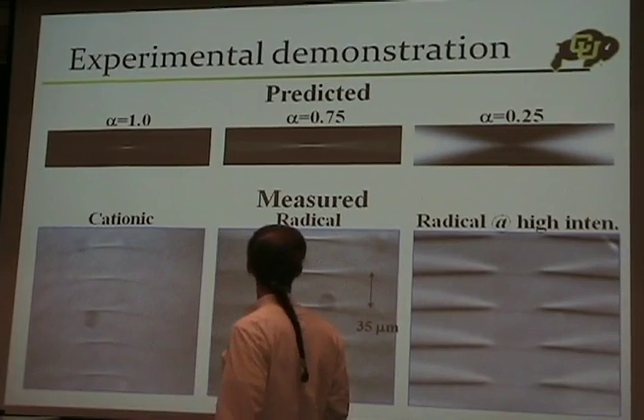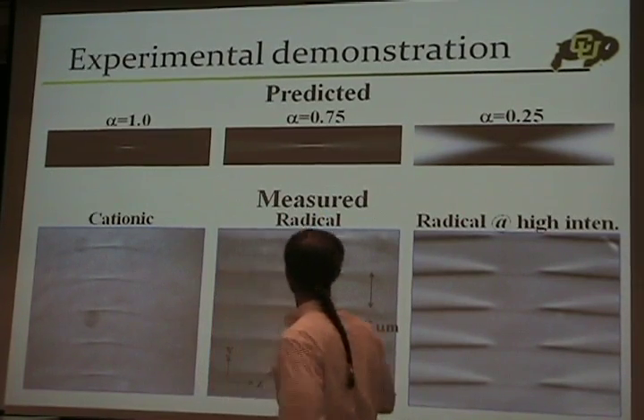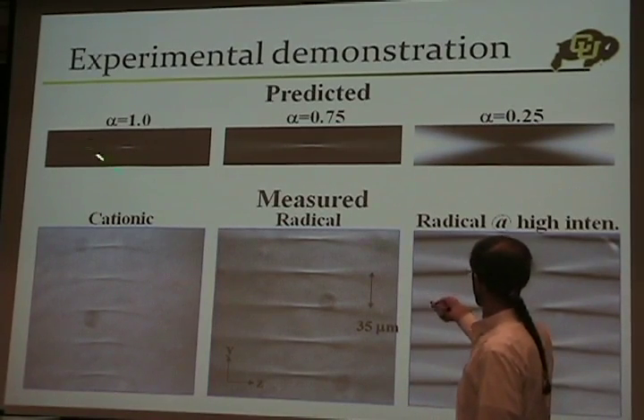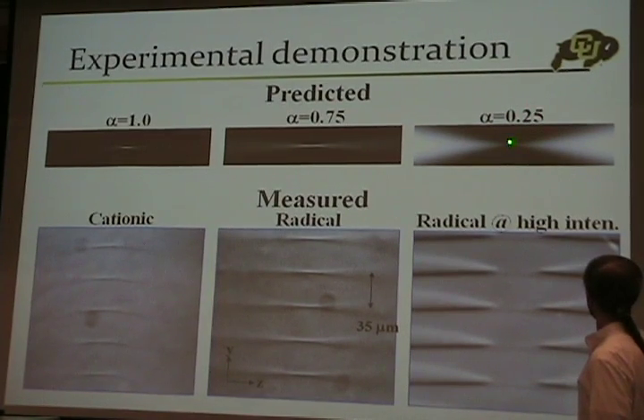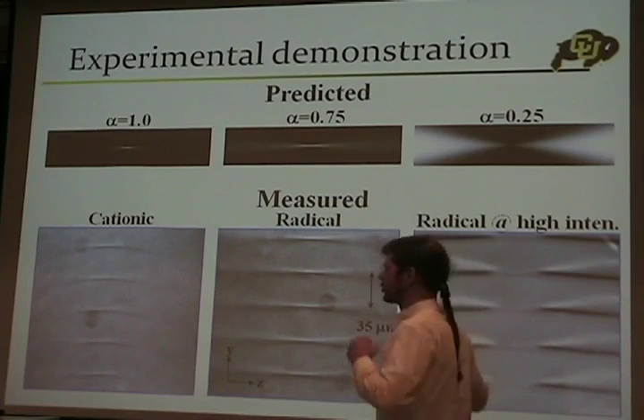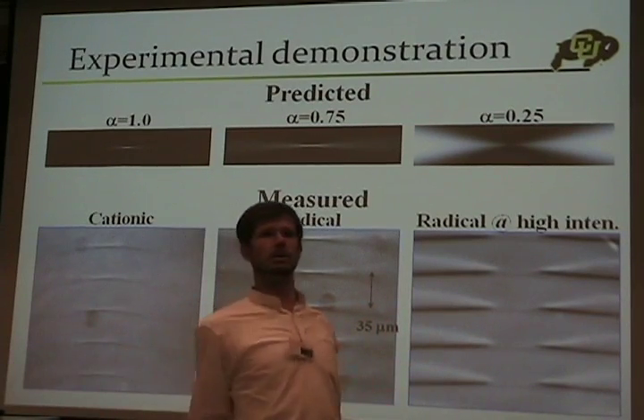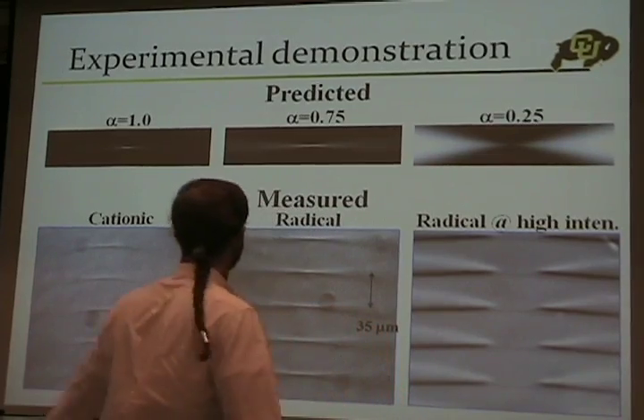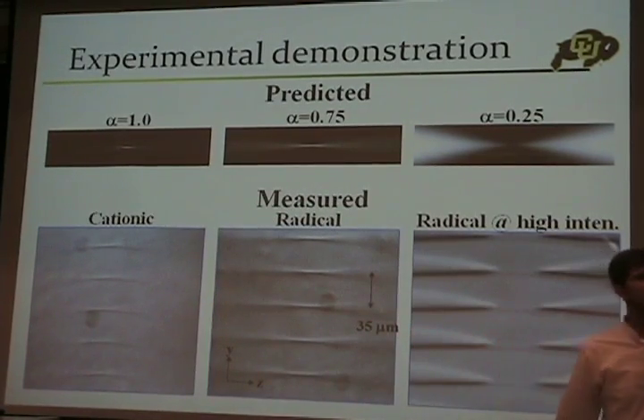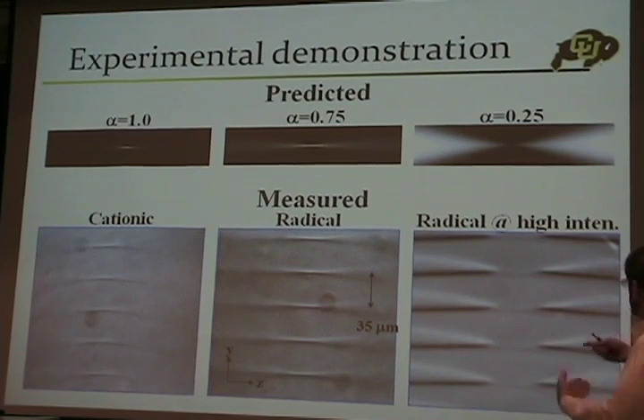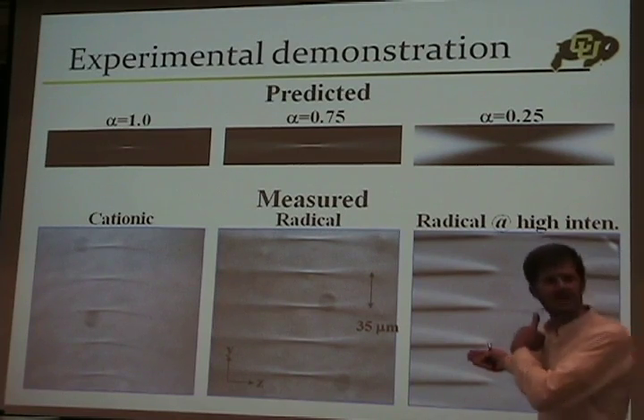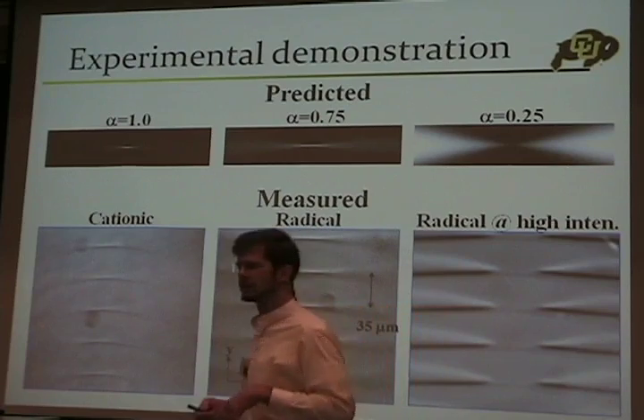Initiation chemistry is one of the things you have to pay attention to, and you can fix it — you can change the formulation. We can use different kinds of initiators and drive different regimes: make these behave linearly, make them sublinear, and we can even go to regimes where the material turns things upside down so that even though the focus is most intense, it responds best out of focus. The images at the bottom are differential interference contrast microscope images — your eye interprets them as rubber sheets that have been illuminated, but what this really is, is a volumetric differential phase image of the material.